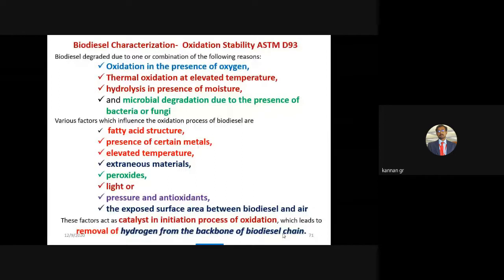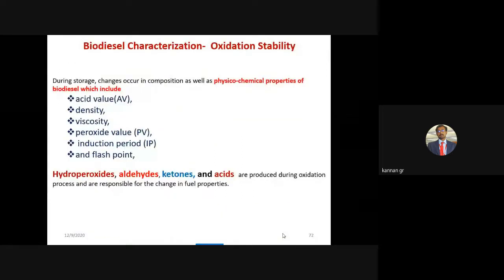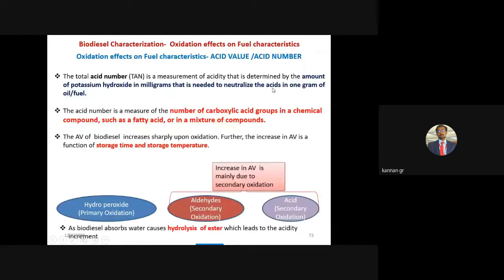During storage, changes occur in composition, particularly acid value, which affects the oxidation stability, density and viscosity, peroxide value, induction period, and flash point. All those things are varying. This variation of properties is mainly due to the formation of hydroperoxides, aldehydes, ketones, and acids in the biodiesel due to oxidation. Here, one interesting point: the acid number of biodiesel keeps on increasing. At the very beginning of this session I told that the acid value is a very good first parameter we need to calculate. Once the acid value keeps on increasing, we need to go for different types of transesterification methods.